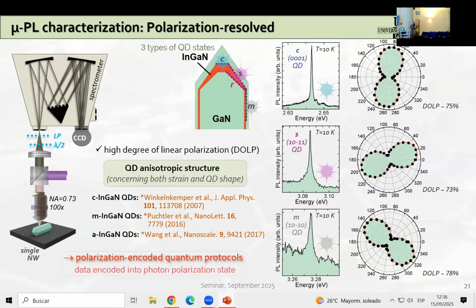We then performed the polarization resolved micro-PL characterization for each type of quantum dots, meaning polar, semipolar, and non-polar. We just randomly chose some wires and some quantum dots formed on those facets. As you can see, they all have a highly linearly polarized light emission with a degree of linear polarization above 75%. This is quite a high degree of linear polarization, which, as I have mentioned before, is important in order to be able to encode information onto the photon polarization state. Now, such a high degree of linear polarization can be ascribed to a particular anisotropic structure of the quantum dot confinement potential, concerning both the shape of this quantum dot potential and also the presence of strain inside the heterostructure, as was previously reported in other polar as well as non-polar InGaN quantum dots.